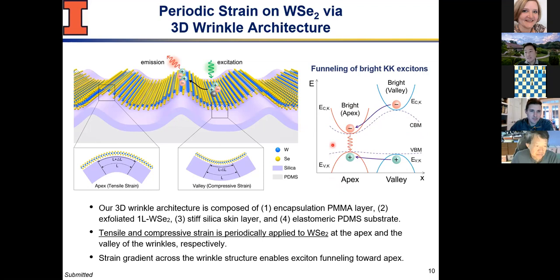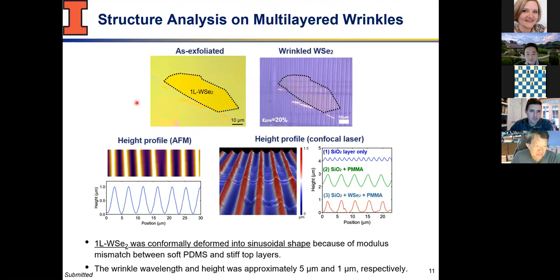And one way to show this experimentally is perhaps if I can excite only the valley, so I do nothing with the apex, but simply excite the valley, and then see if the exciton ever will travel to the apex at all. I mean, there will be natural diffusion when you dump energy, lots of excitons will be created. So you have a diffusion around the valley portion of the material, but there might be an opportunity for them to travel to the next apex, and then maybe we'll see them right there, even though we didn't do anything at that particular point. So that's the thought, and that will be the direct proof of this exciton transport along the strain gradient. So that's what we wanted to do, and that's what I'm going to show you briefly.